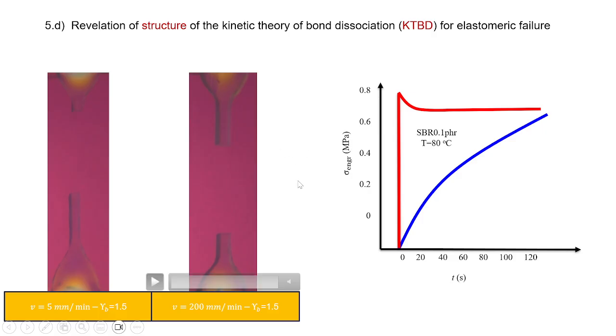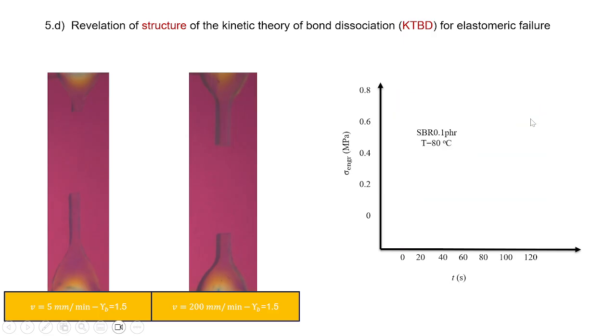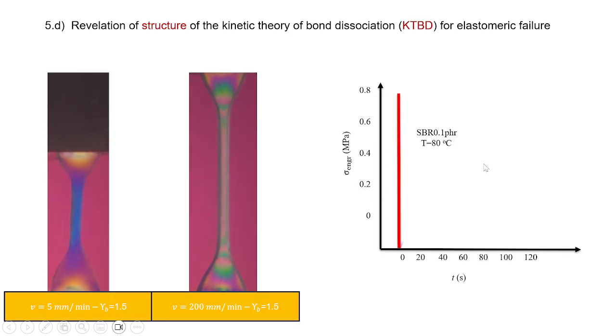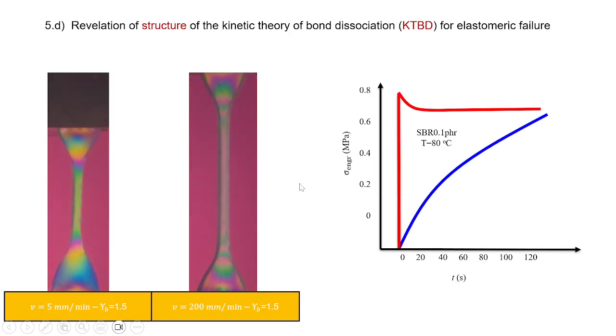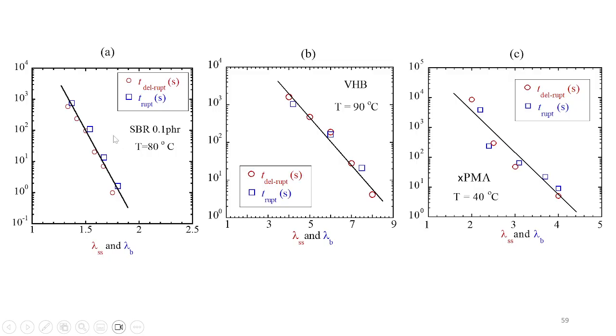And then the system just waits until the network expires, in the red. Whereas the continuous stretching was so slow, you already eat up all the time. And so by the time you reach the expiry, they all expired at about 100 seconds. So that actually tells you the structure of my theory. I'm not going into details, but basically you can do this for different rates and find the time scale revealed by step strain waiting versus the time consumed or elapsed during continuous stretching.